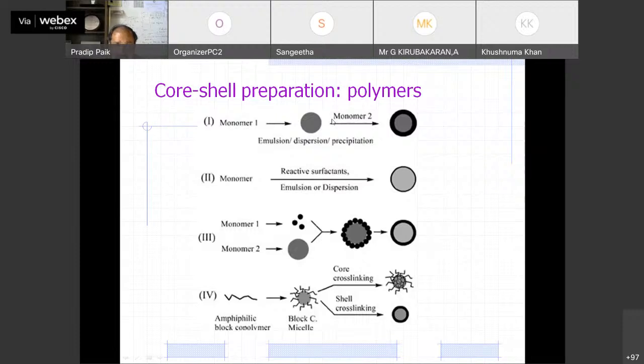Otherwise, what will happen if monomer 2 creates a repulsive force on the surface of the core? This monomer 2 will not be deposited. This is always true for other cases also. If you take metals or different composite materials for core shell, there will be a gap or repulsion. So if there is no affinity, then monomer 2 will not be deposited after formation of the polymer. This is the basic principle you have to keep in mind.